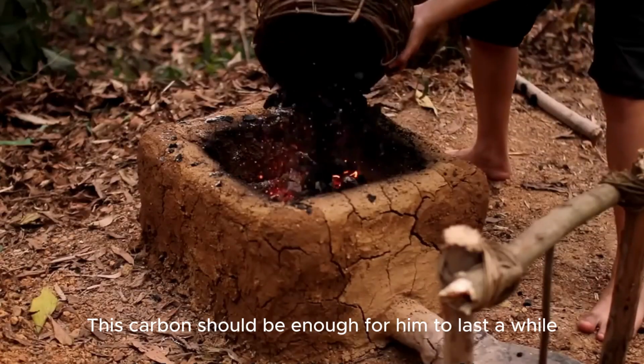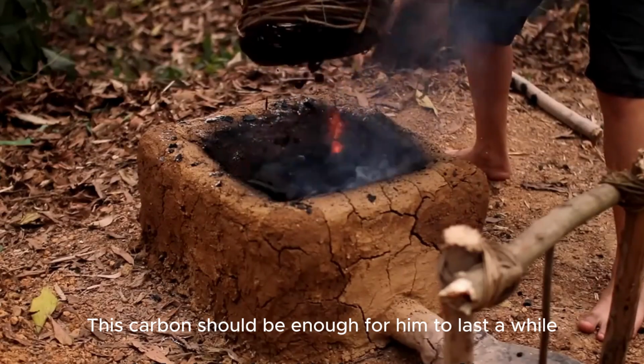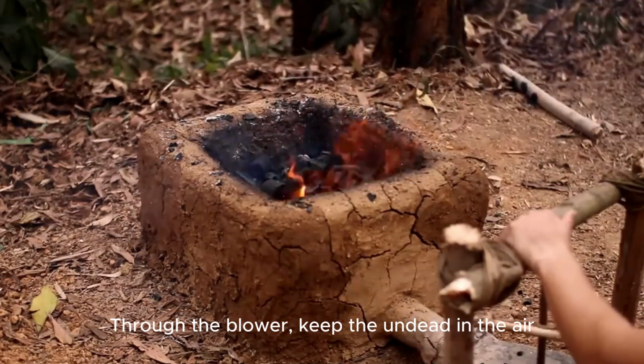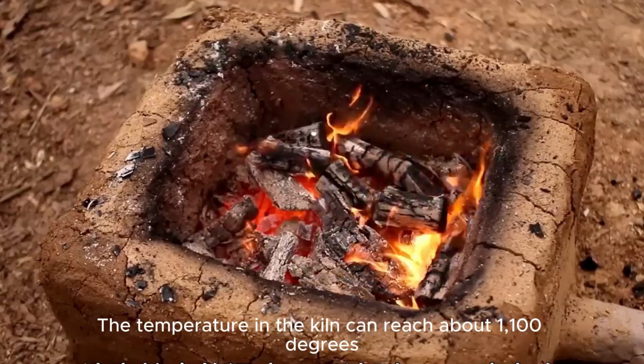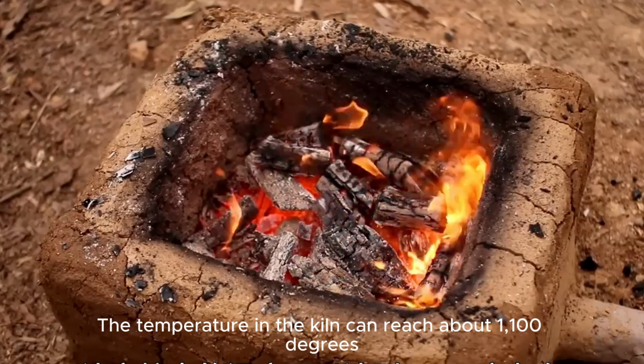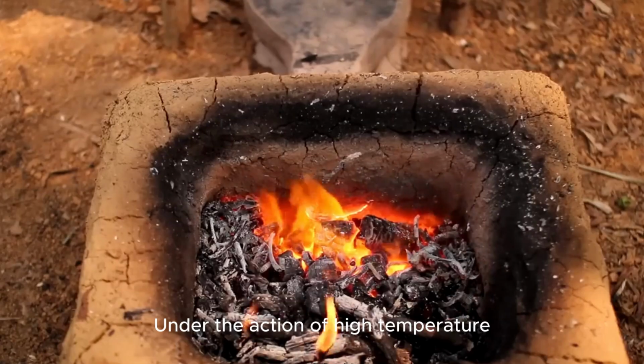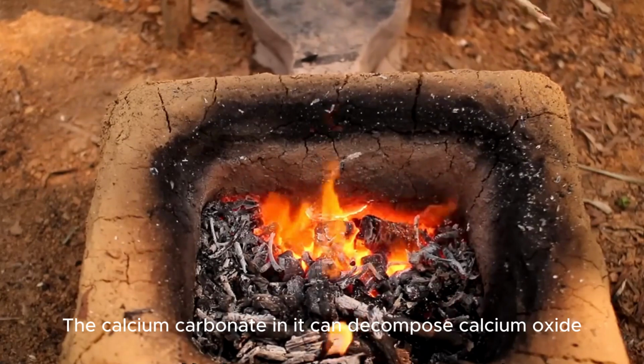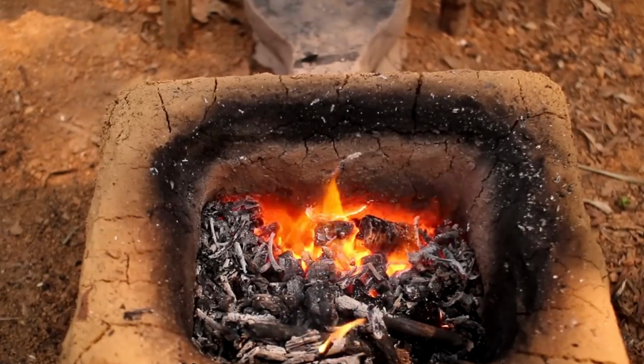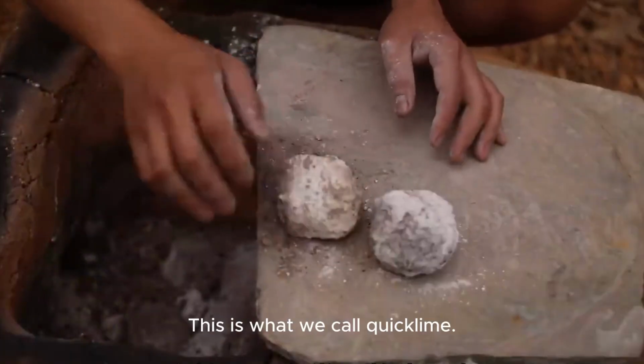This carbon should be enough for him to last a while. Through the blower, keep the fire going in the air. The temperature in the kiln can reach about 1100 degrees. Under the action of high temperature, the calcium carbonate in it can decompose into calcium oxide. This is what we call quicklime.